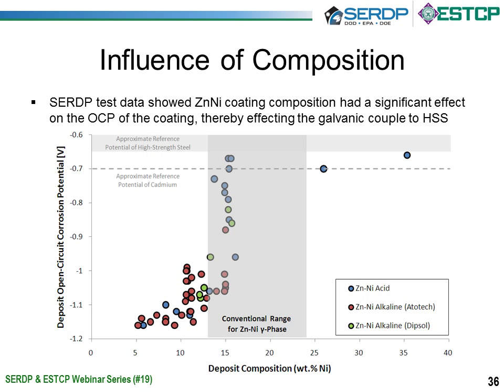One of the other things that we found in this project is we measured the open circuit potential of the different materials that we produced using different methods, plotted that against the composition of the alloy, and compared it to that for cadmium as well as that for high-strength steel. So in order for the material to provide sacrificial corrosion protection, the open circuit potential needs to be below that of high-strength steel. However, you want to be as close to high-strength steel as possible in order to minimize the galvanic couple, which can potentially lead to